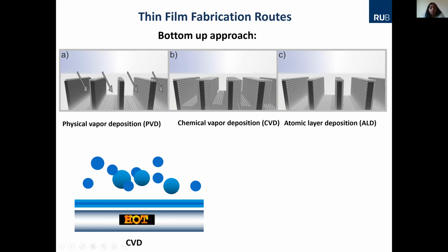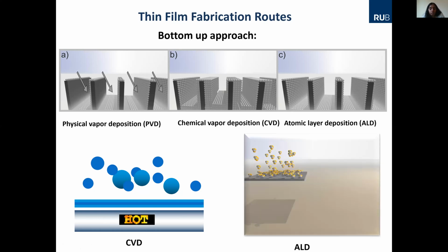Then later on, another variation of CVD, and that's called atomic layer deposition. As the name indicates, here you can actually grow thin films layer by layer at atomic thickness control. So very precise thickness control. And this is actually the method that is being used by Intel or IBM to grow these very thin materials for such applications. So how does it work? So you can think of having a substrate. Here you see on the left side with CVD that you have a molecule or a precursor that decomposes on a hot substrate. The byproducts that are liberated due to the decomposition, basically the organic part, are released and pumped out, and only the inorganic material is deposited.